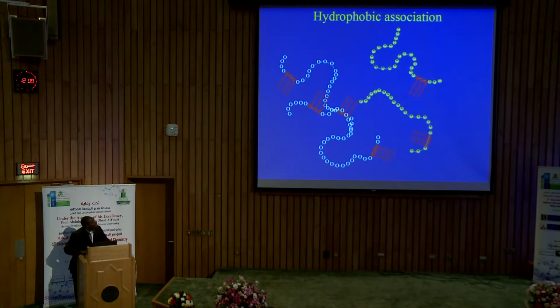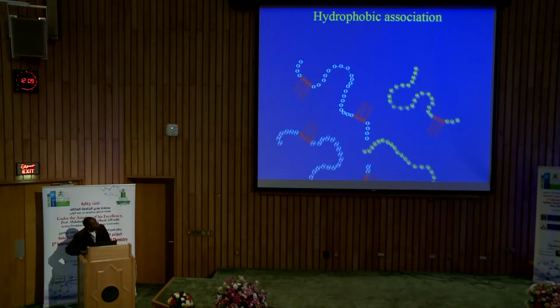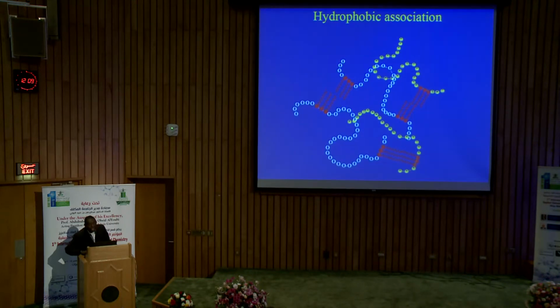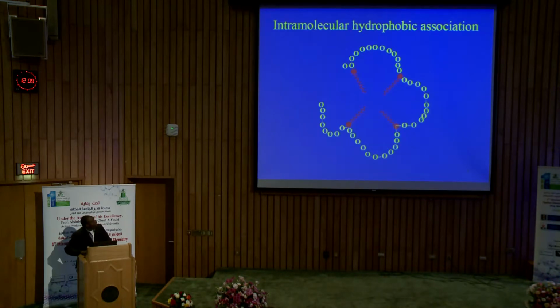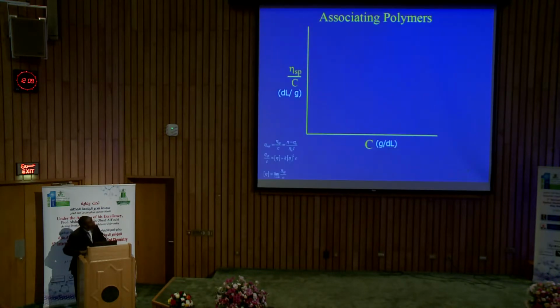So when you have a block arrangement of the hydrophobes within the polymer chain in aqueous solution, these chains can associate together to form a network, and this network can lead to high hydrodynamic volume and an increase in viscosity. And this is our main interest. Now, looking at the other side, intramolecular association: the hydrophobes interact with each other intramolecularly, leading to a smaller volume of the polymers.